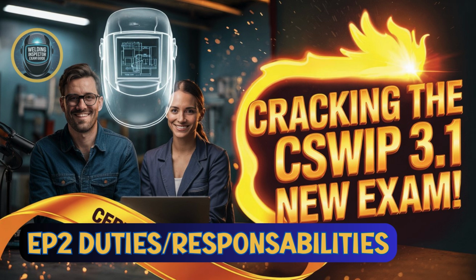Precisely. They might also do a dimensional survey. Check the final dimensions of the whole assembly against the drawing, because welding can cause distortion. Okay. Does it fit? Right. They confirm any other NDT, like ultrasonic or radiographic testing, has been done and the reports are in. If repairs were needed, they monitor the repair to make sure it follows the approved procedure. So they check the fixes, too.